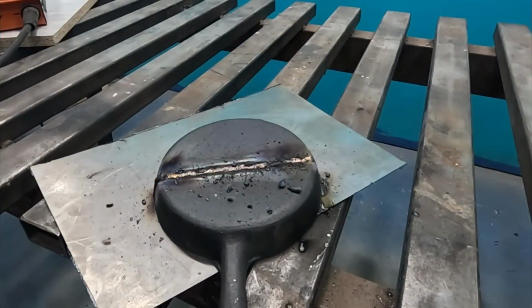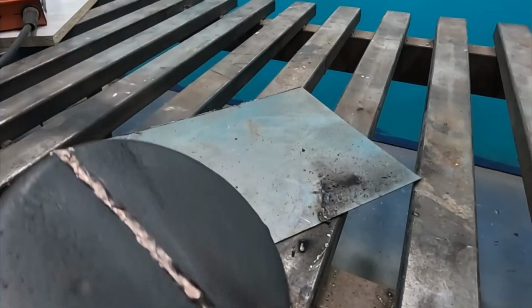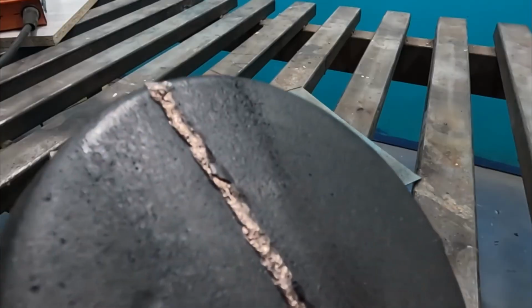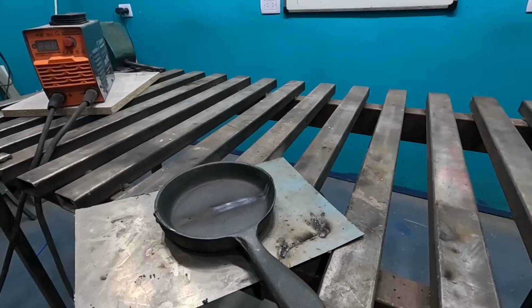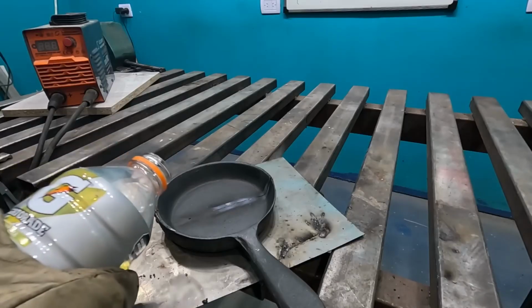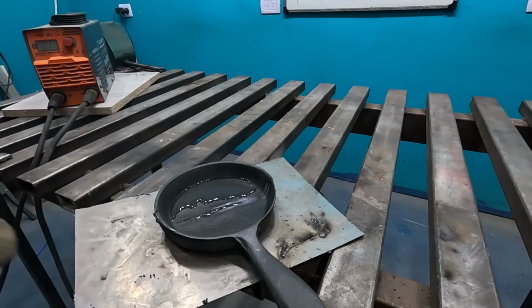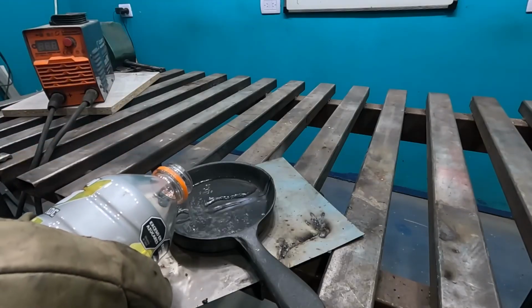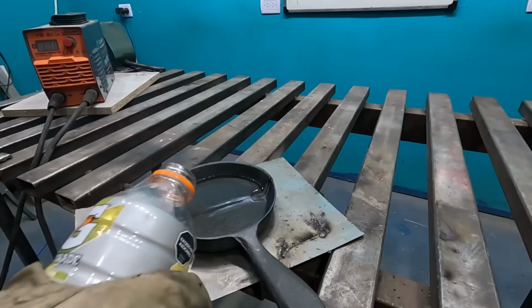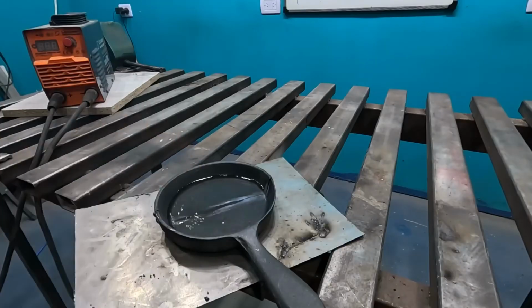That's how the weld turned out. As you can see, you can notice a bit of a copper color. Although I noticed it lacked a bit of penetration, the bead turned out pretty good. And now, to see if it's really sealed, I'm going to put a little water on it to see if it leaks. When I added water, it didn't leak a single drop, so it's well sealed.